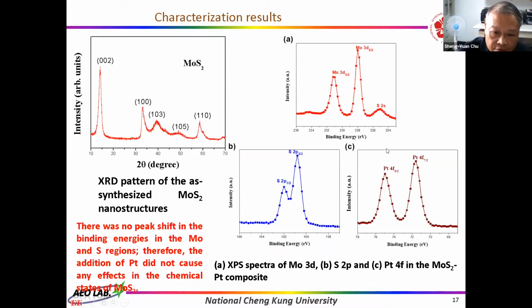And these three figures show the XPS spectra of Mo 3d, S 2p, and Pt 4f of the MoS2-Pt composite. From these figures, we can see there are no peak shifts in the binding energy in the Mo and S regions. Therefore, the addition of Pt did not cause any effects on the chemical states of MoS2.